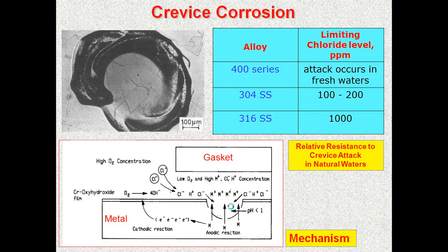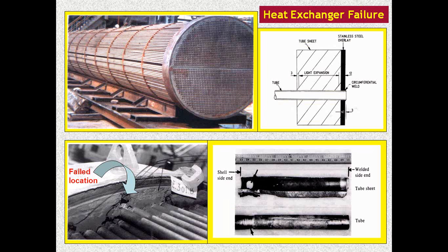And I will tell you, it may appear like a very small type of corrosion, but you see such a huge heat exchanger used as a carbamate heat exchanger in a fertilizer industry. The tube to tube seat of this joint had some poor tube to tube expansion, and there was a gap here of few micron. The gap then led to severe corrosion, and you can see that there was a leaking, and within a short period this brand new heat exchanger, which was imported, got into a problem mainly because of the crevice corrosion that took place between the tube and tube seat.